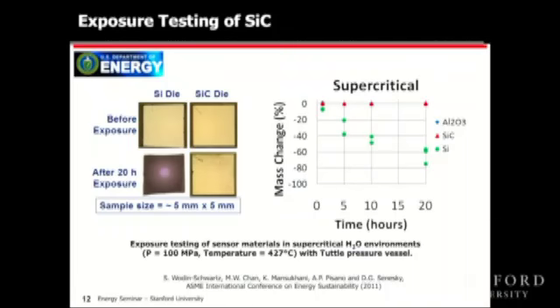This plot here is showing the mass change over time. The red dots here show silicon carbide, the percentage change in mass. No measurable change in the mass. The silicon shows 80% change in the mass over 20 hours of exposure.